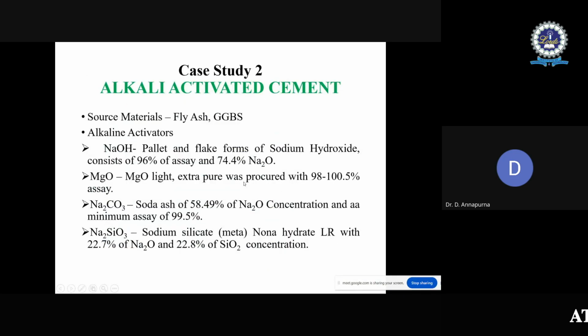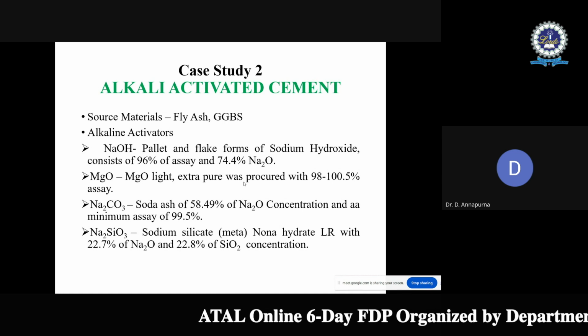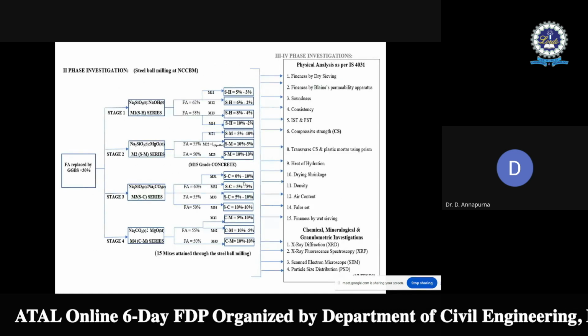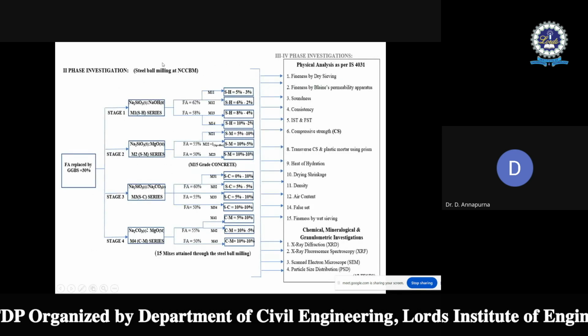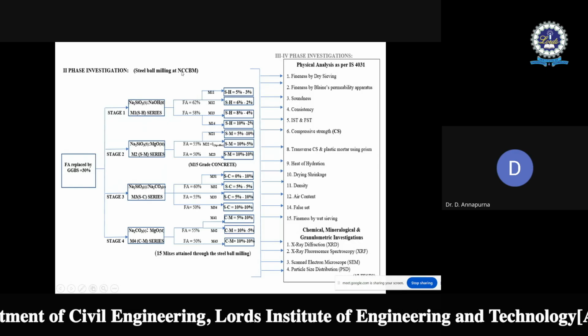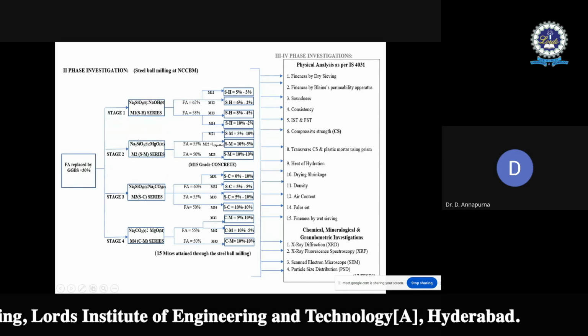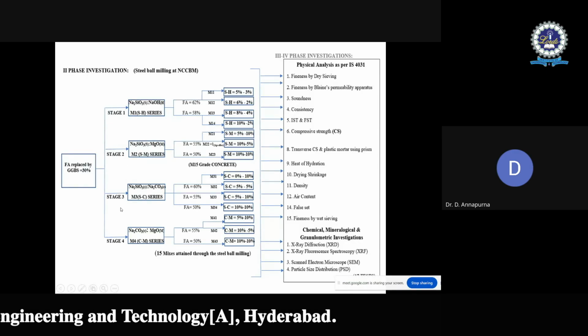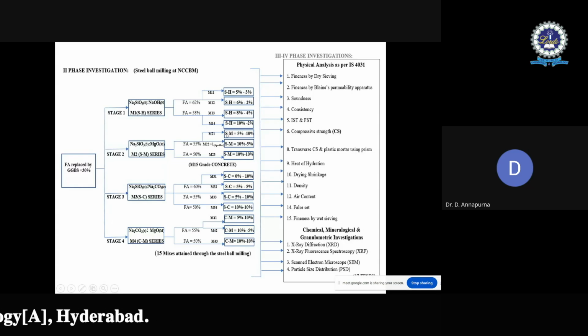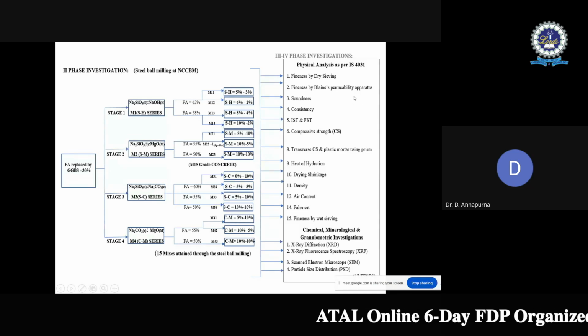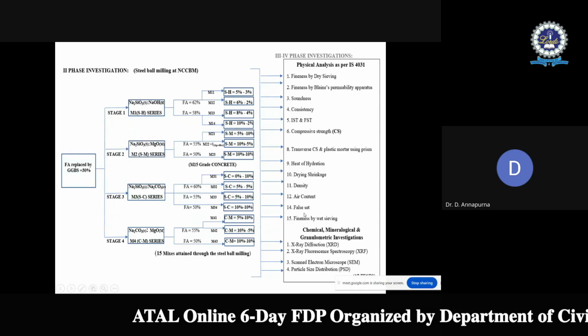As this cement needs to be prepared, these materials are mixed in dry form and ground to a fine powdered form. For the grinding process, steel ball milling is used at NCCBM. This particular work is conducted in different stages, stage 1 to stage 4, and on the prepared geopolymer cement or alkali activated cement, different tests are conducted as per IS 4031.